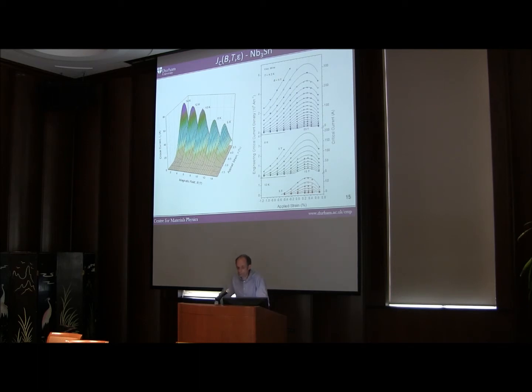You want that to be as high as possible. You can see from these graphs, the different colours correspond to different temperatures. But in actual fact, when you put them under a little bit of compression, or a little bit of tension, things actually get a bit better, if you look very closely, before the curve starts to drop off. The materials are designed such that you can put strains on them up to a certain level without doing too much damage to the critical current they can withstand.